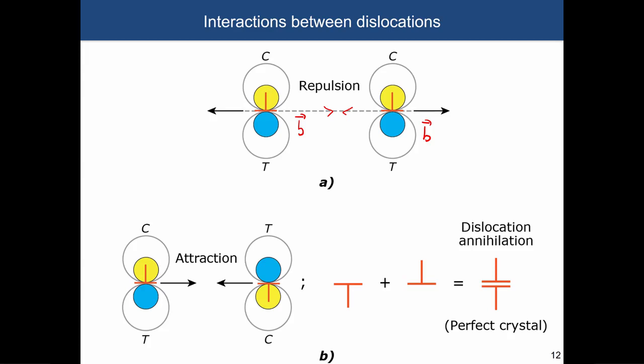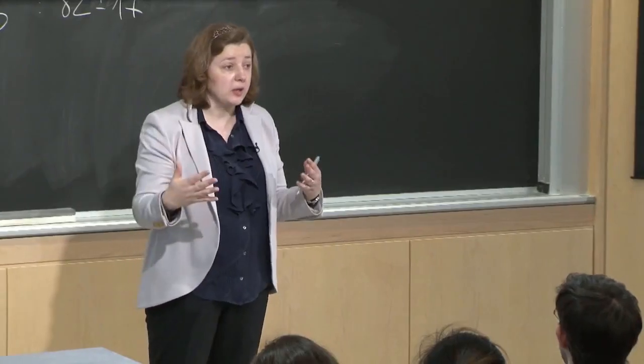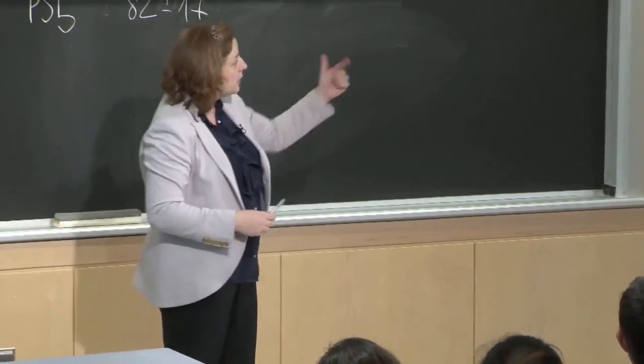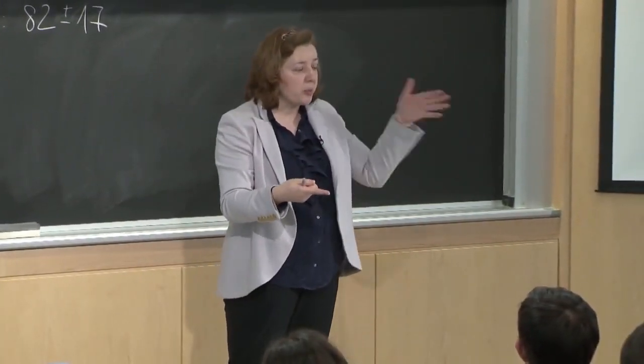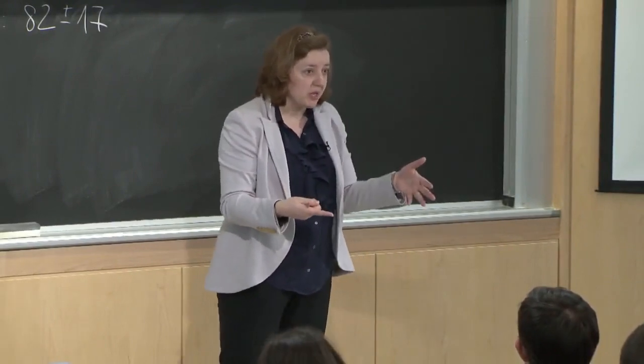And again, you can try to understand this more intuitively. If you have this dislocation here, and there are planes that are deformed around it, so there is another dislocation here. So for this first dislocation to propagate, ideally, the propagation will be relatively easy if the crystalline planes are perfect, right? But if you find another dislocation, what that means is that the strain around this dislocation somehow prevents the first dislocation from moving.